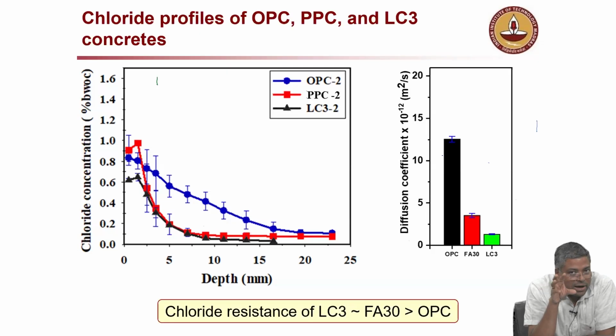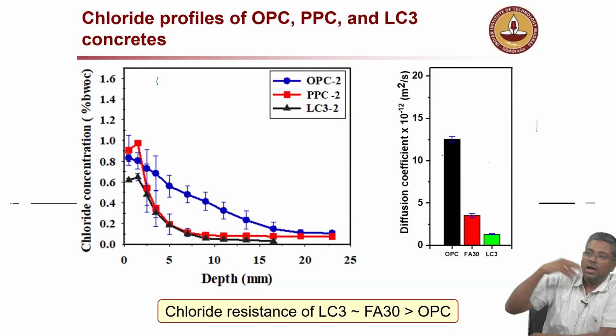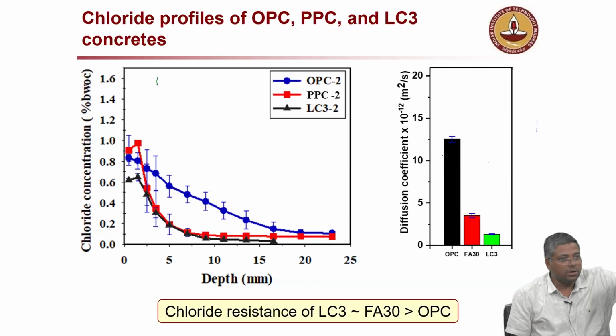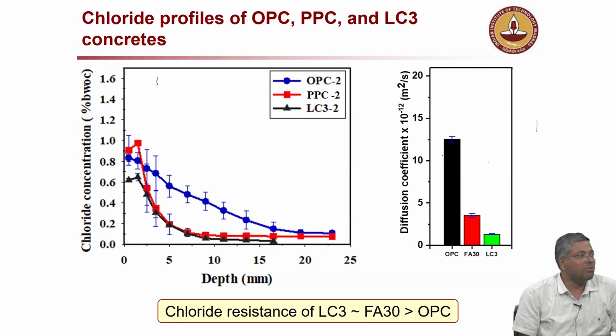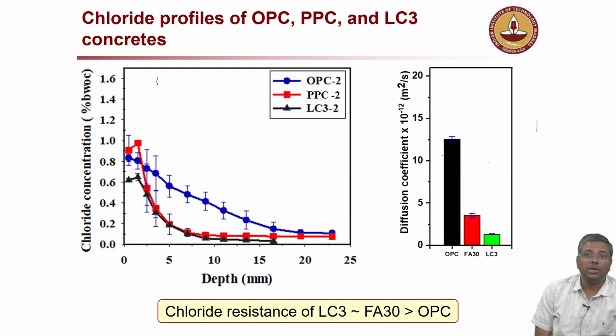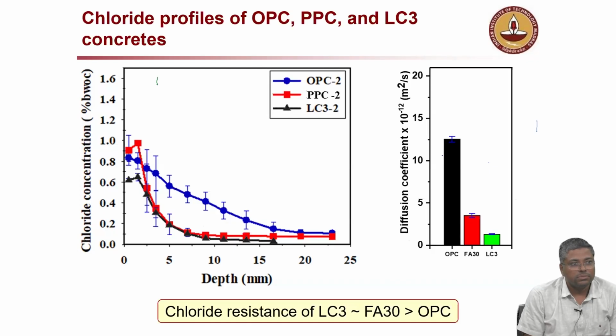Okay, this is a graph obtained from a laboratory study where we put different types of cylinders in chloride solution. After 35 days, we took them out and then made this chloride profile. How much chloride has penetrated into the concrete? Okay, very clearly OPC is performing very good or bad? Bad.